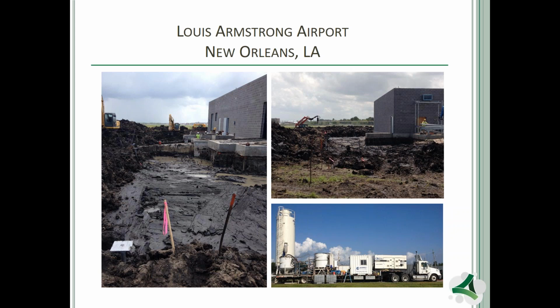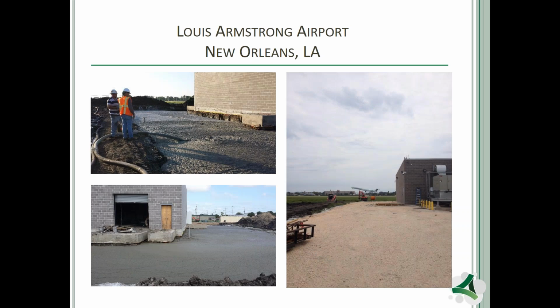To create the zero loading factor in that area, they dug out 4 feet of muck, for lack of better words. They placed down a silt fabric and then replaced it with 4 feet of pervious cellular concrete, and then placed the crushed lime over top of that, and then the final pavement over that. Today, that project acts like a great big sponge because it sits right at the water table. So as the water table rises, it is absorbed into the pervious cellular concrete, and as the water table drops, it is released again.